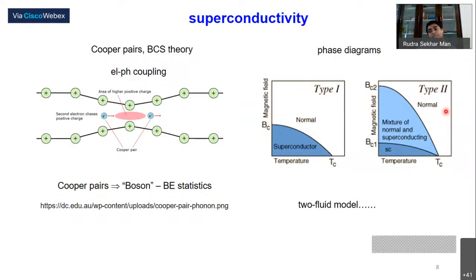And if you have a type 2 superconductor, that is more different. They talk about electron pairing, how this pairing happens, and there are different mechanisms and different phases. Type 1 is very similar, but for type 2 superconductors there are theories of a mixed phase, meaning you have normal conductor and superconductor together. When you reach Bc1, you don't destroy the superconductivity fully, rather partially. But at Bc2, you suppress the superconductivity. In between you have a state also called the vortex state, which is a mixture of states. And in this case, the Tc was found to be a bit higher, above nitrogen temperature.